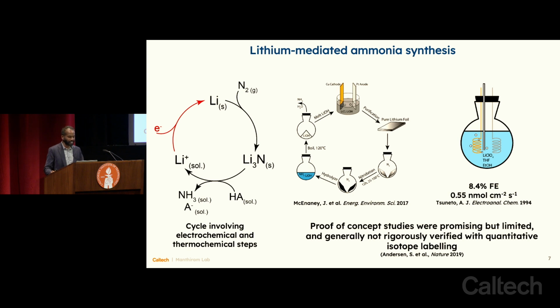We can look back about 5 years ago, to a demonstration that showed how you could take lithium metal that's plated out of a lithium chloride, lithium hydroxide bath operating at 400 to 500 centigrade. You could cut that lithium metal up and put it into a beaker, introduce nitrogen gas, and make lithium nitride. You could then introduce water as your proton donor, make ammonia, and boil off the ammonia in water. You'd leave behind lithium hydroxide, and you could dump that back into the first bath and continue around this cycle.